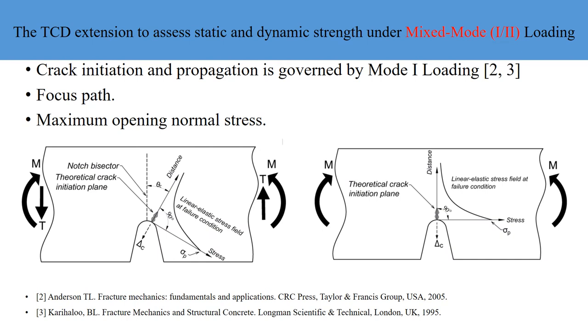The new extension of the TCD method starts by explaining the simple rule to determine the orientation of the focus path under mixed mode loading, which is essential to apply the TCD method. In concrete, crack initiation and initial propagation is governed by mode 1 loading. It is assumed that the orientation of mode 1 cracks is along those directions where the opening normal stress is maximized, tangent to the surface of the crack initiation site. The focus path is a straight line emanating perpendicularly to the maximum opening normal stress.